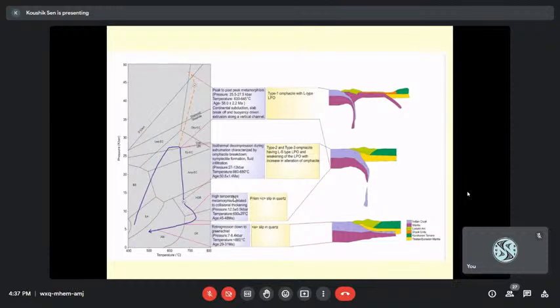One is Dipto's paper, I think from 2021, and Long is 2022. So they have talked in detail about the slip systems present in the host Puga gneiss. I am talking about the quartz slip systems present in the metabasic enclaves within the Puga gneiss. So again, the LPO we are getting from quartz, I would prefer to correlate with this later high temperature overprint event followed by retrogression events. I would say that this quartz LPO has nothing to do with peak metamorphic conditions, because it is very unlikely that this quartz will hold its high pressure slip system even after so many deformation events and retrogressions and all that.